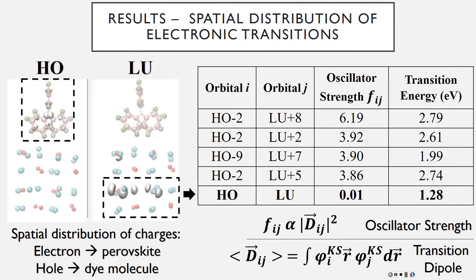But then if we look at states that do produce spatial separation of charges, like our HOMO and LUMO state here, where the electron would reside on the perovskite and the hole would reside on the dye, we do get charge separation there, but it has a very low probability of occurring because there's not much spatial overlap between the orbitals. They're on different sides of the material, basically.